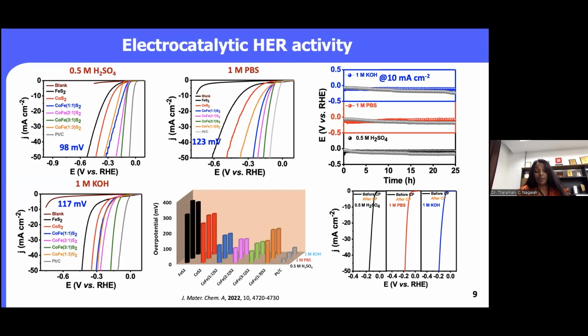In order to apply it for the application, the stability test is very important. In this case, we have done the stability test in all the media at 10 milliamp per centimeter square for about 25 hours. And also we have compared this activity with respect to the state-of-the-art, in this case platinum carbon. As you can see, the catalyst is almost stable in all the media up to 25 hours.